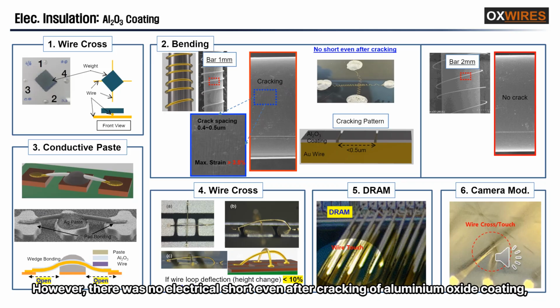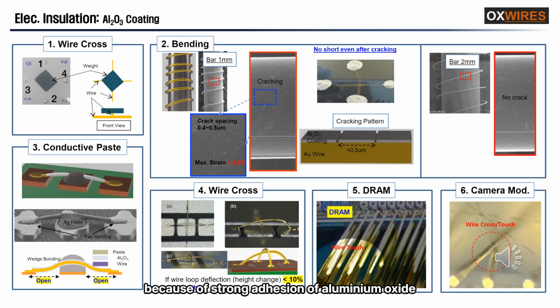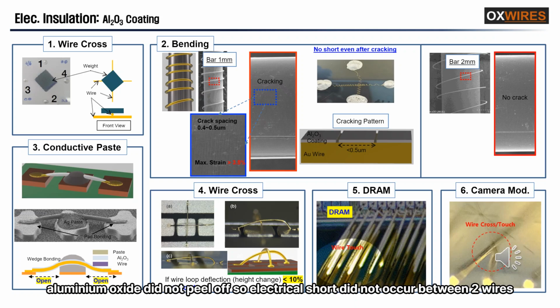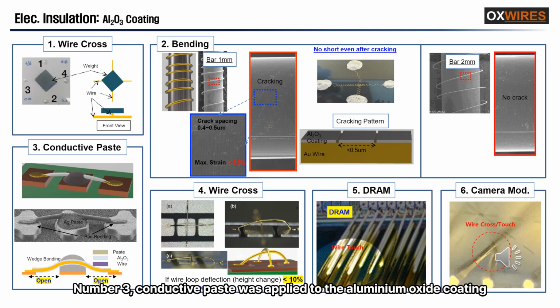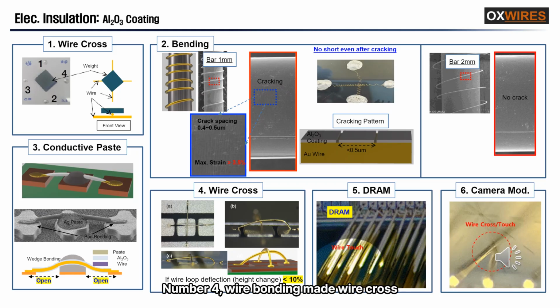However, there was no electrical short even after cracking of aluminium oxide coating, because of strong adhesion of aluminium oxide. Looking at the cracking pattern, even after the cracking like a mud crack, aluminium oxide did not peel off, so electrical short did not occur between two wires. Number 3. Conductive paste was applied to the aluminium oxide coating. No electrical short.